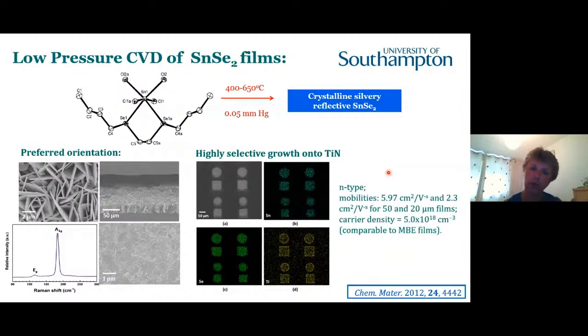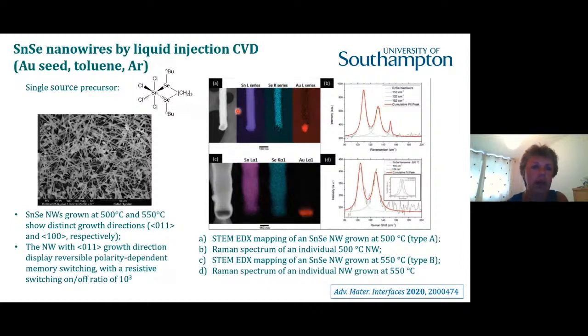But it turns out that if we increase the temperature, we can also deposit the tin monoselenide. And we've collaborated with colleagues in the University of Cork, Justin Holmes and his team in Cork in Ireland. We've been working with him to use our precursors in a liquid injection CVD experiment. Now, in this case, we're using gold nanoparticles on a silica substrate, and we're using a toluene solution of the precursor. And what we're able to do is, depending on the deposition temperature, we can grow arrays of these tin monoselenide nanowires. These nanowires are depicted in the transmission electron micrograph at the top here.